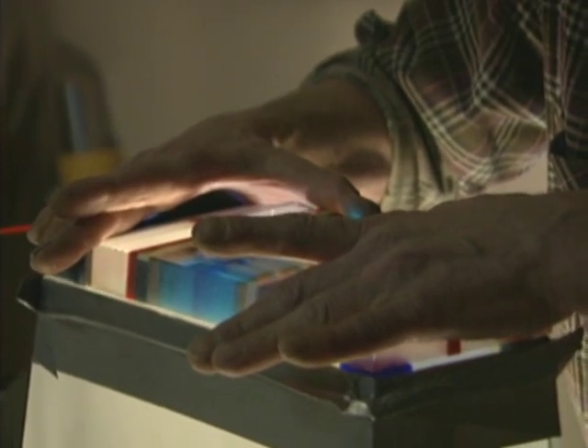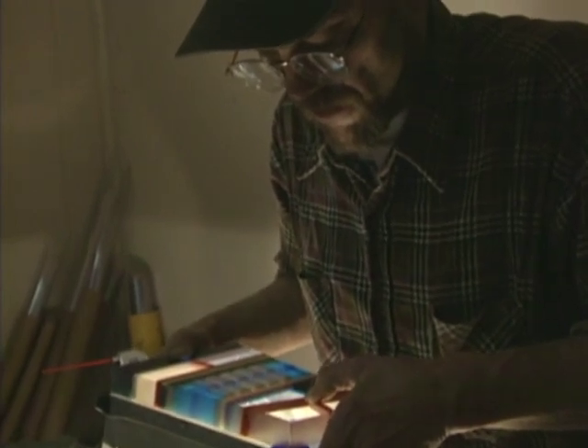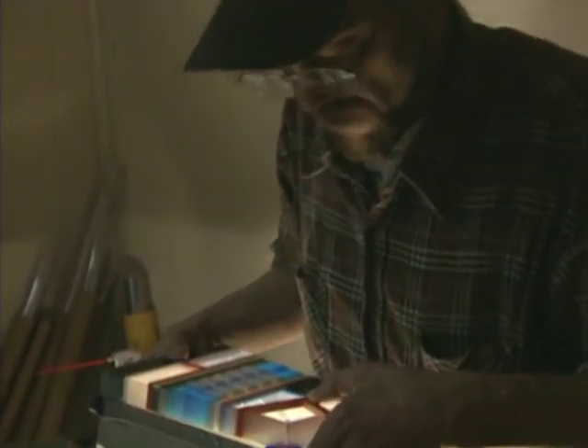The laminating process takes about 2 days before we can go back in and recut or do any additional work on the top panel that we're working on. The resin cures in about 7 days at 70 degrees. And what we do is we speed up the cure to about 30 hours by preheating it to about 106 degrees and then maintaining a constant temperature within the laminating room.